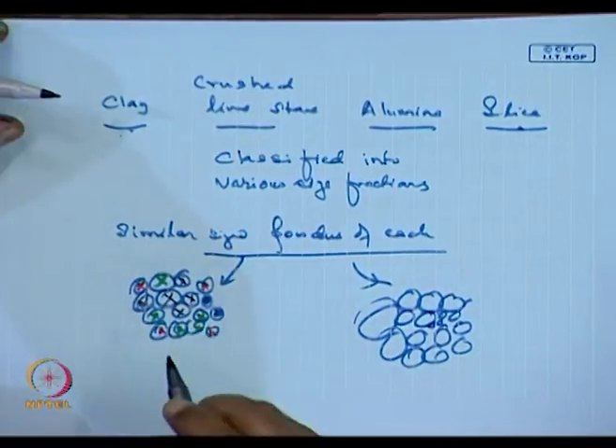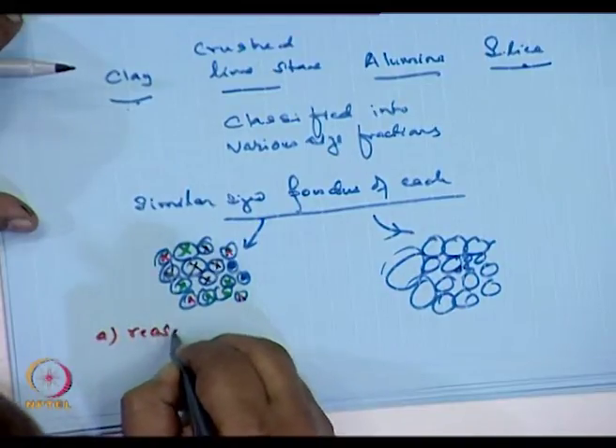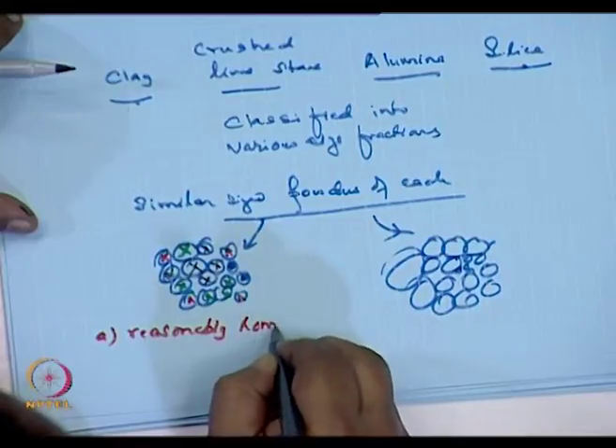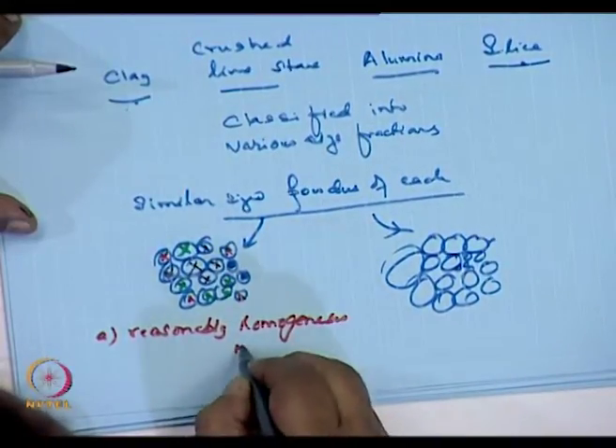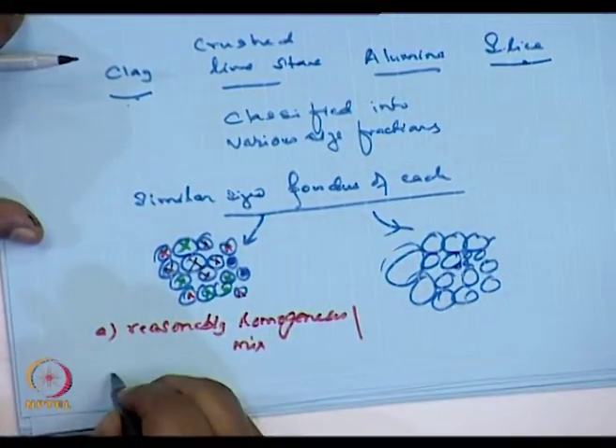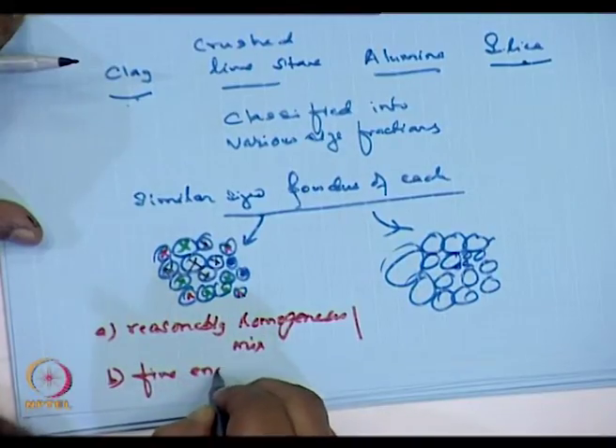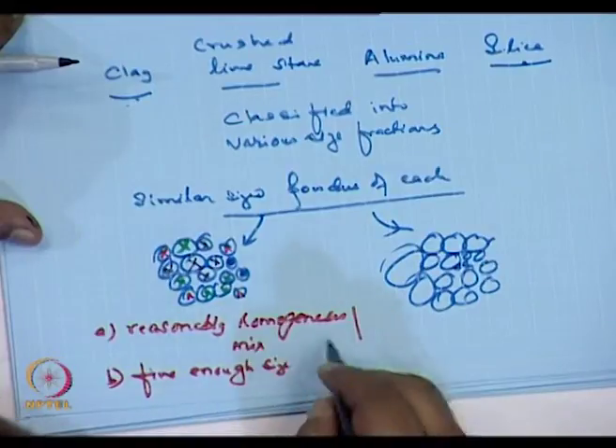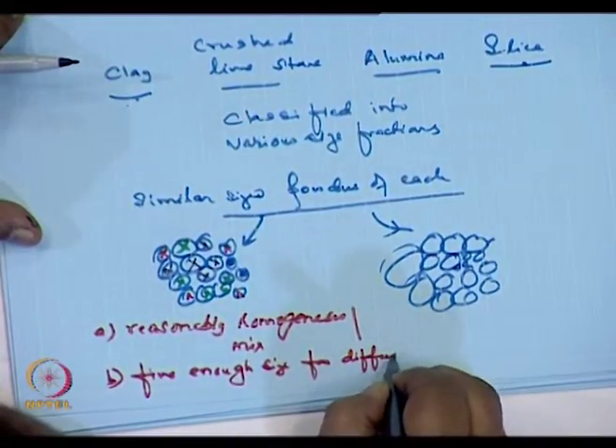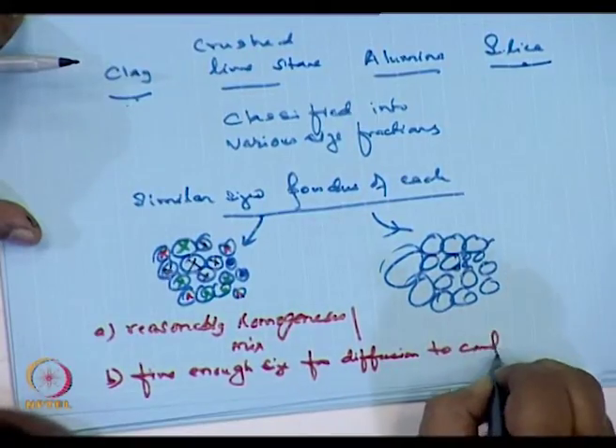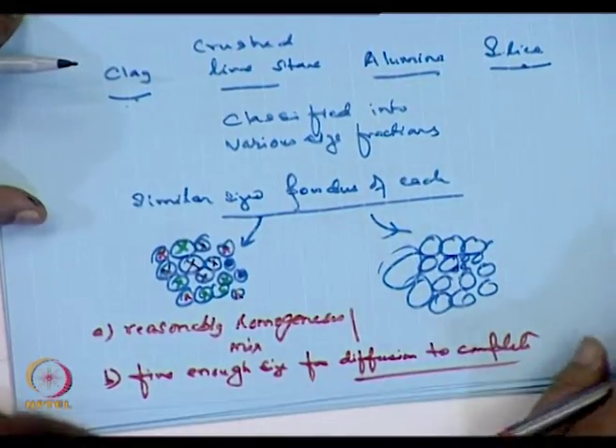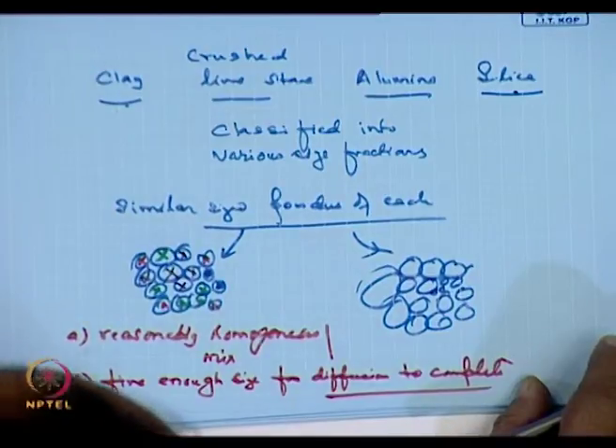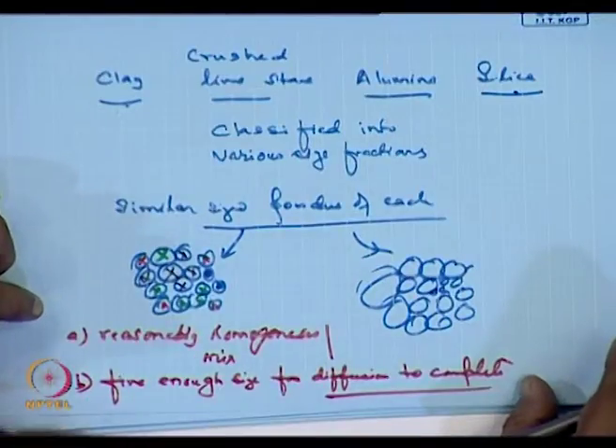So, the first thing, for example, in the cement industry, where I talked of these powders, we need a reasonably homogeneous mix. This is paramount. Second, fine enough size for diffusion to complete. These are two major issues which have to be addressed in dry grinding. The powders have to be homogeneous.